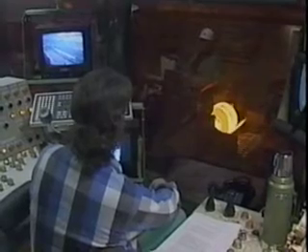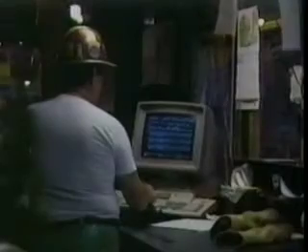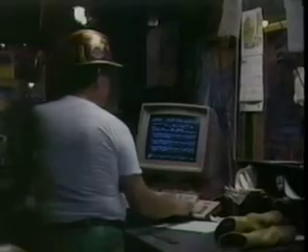A hot strip coil box processes this 2,000 degree, 1-inch thick transfer bar into a coil form for temperature conservation and equalization. Next, the steel is uncoiled to the finishing mill at an even temperature profile, which helps achieve the temperature and thickness control needed for the customer's order.